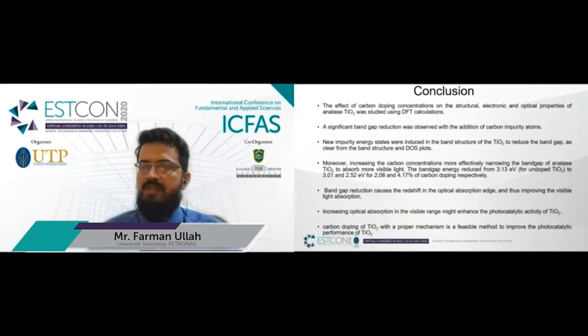It is also mentioned that as we increase the concentration from 2.08 to 4.17% of carbon doping, the band gap energy is reduced from 3.13 electron volt to 2.52 electron volt. A band gap reduction causes the redshift of the optical absorption edge and thus improves the visible light absorption. Also increasing the optical absorption in the visible range enhances the photocatalytic activity of TiO2. So carbon doping of TiO2 with a proper mechanism is a feasible method to improve the photocatalytic performance of TiO2.